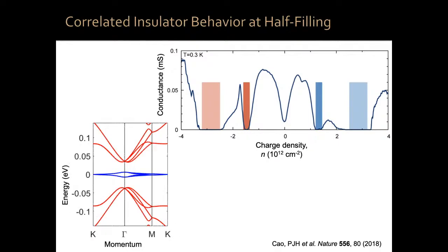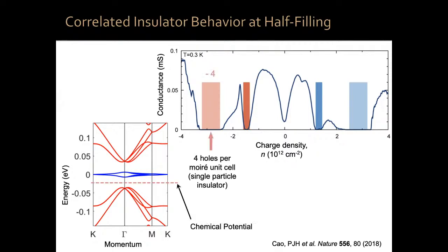Remember that these are the flat bands, okay? So from charge neutrality, from 0, I can add electrons to this band until I get to the very top, or I can remove electrons from this band until I get here to the bottom, okay? In order to do that, to have the chemical potential in this region, to empty this band, I have to take away 4 electrons per Moire unit cell, or add 4 holes per Moire unit cell to my electronic structure. Remember number 4? I told you it will appear again. Here it appears again, okay?